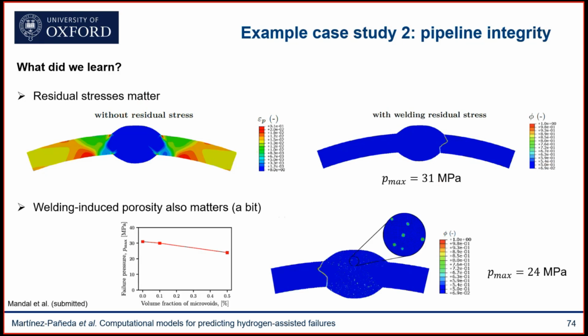We also wondered about whether the porosity that comes naturally from the welding process will play a role. We found that it plays a little bit of a role, but not significant. So this only played a role in the X80. And as you can see here, when we move within a sensible range of volume fraction of microvoids, we only see a small drop in the critical fracture pressure. We go to 24 megapascals for this, 0.5%.